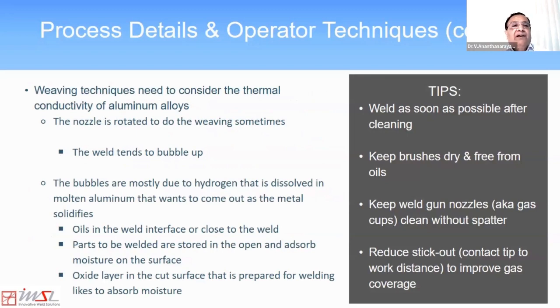Weaving techniques also need to consider thermal conductivity of the alloys. The nozzle is rotated to do the weaving sometimes. And one of the problems with welding aluminum is the weld tends to bubble up. The bubbles are mostly due to hydrogen that's dissolved in molten aluminum. Oils at the weld interface, or parts to be welded stored in a moist atmosphere, or the oxide layer on the cut surface are causes of this moisture content, and also the shielding gas. And cleaning these up usually helps, and weld as soon as possible after cleaning, and keep brushes dry and oil-free, and keep welding gun nozzles clean, and reduce the stick out.